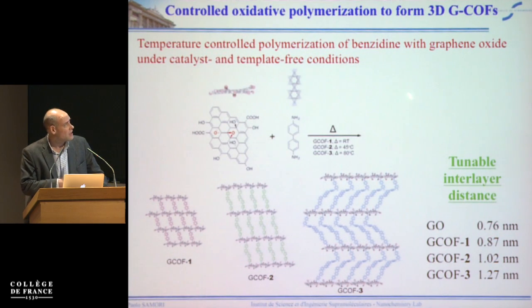So you can see that when we combine the graphene oxide with benzidine at room temperature, we form essentially a layer-by-layer structure with a single benzidine connecting distant layers of graphene oxide. If you do this at 45 degrees, the cartoon is such that you have a dimer of benzidine, and at higher temperature, like 80 degrees, you have an oligomeric form. This kind of growth is a way to tune the average distance between the layers of graphene oxide, which is well reflected by the X-ray diffraction data that have been recorded. You can see that we gradually increase the average distance between the layers.